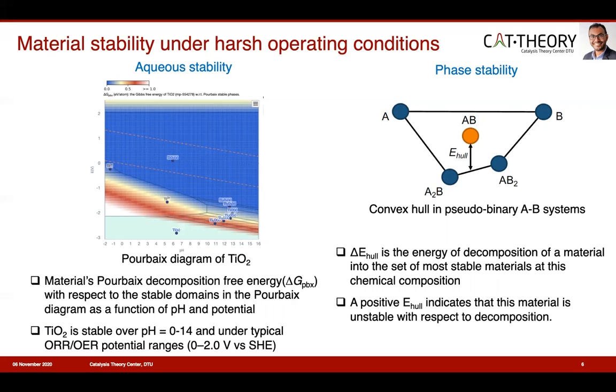Aqueous stability of a material can be determined by computing the material's Gibbs free energy with respect to stable domains in the Pourbaix diagram as a function of pH and potential, as you can see here. For example, titanium dioxide is stable over pH 0 to 14 and under typical ORR and OER potential ranges. On the other hand, E_hull is the energy of decomposition of a material into the set of most stable materials at a particular chemical composition. This thermodynamic phase stability can be used as a metric to estimate the synthesizability of the candidate material. So the higher the E_hull, or if it is positive, the more unstable the material is and synthesis will be challenging.